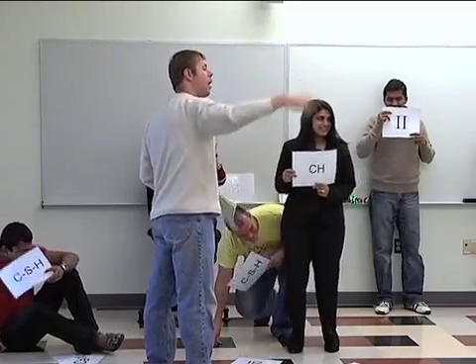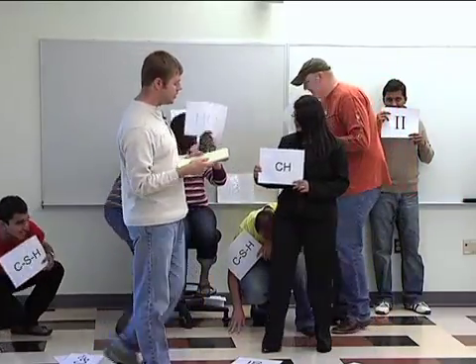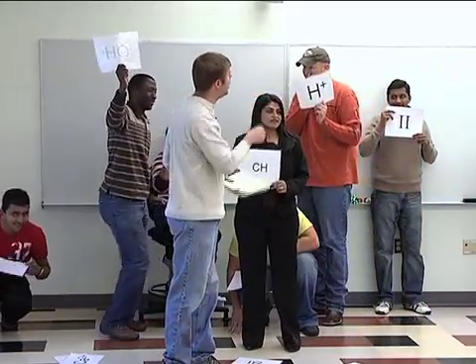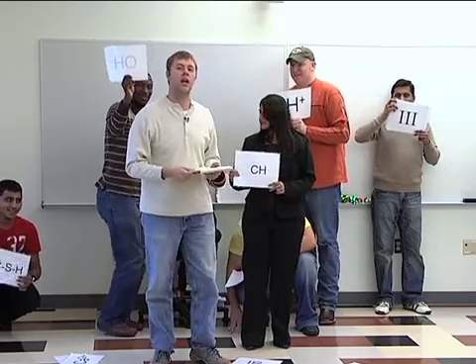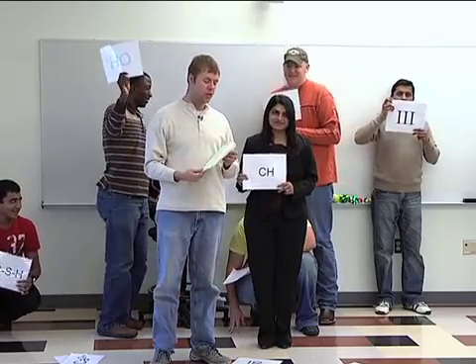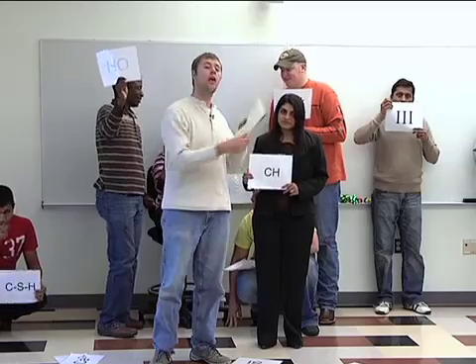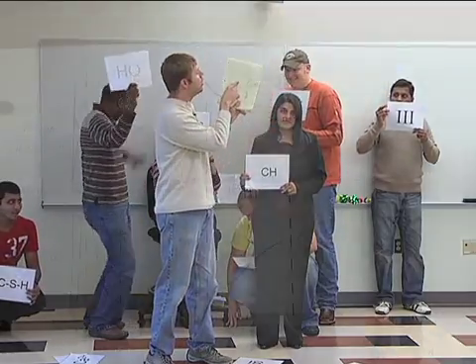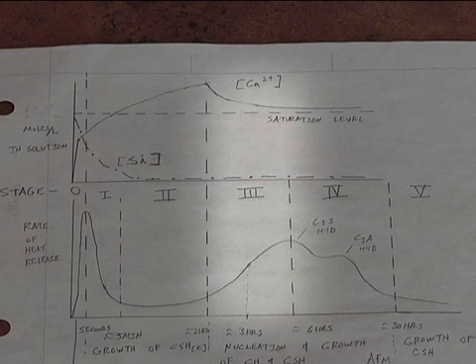All of a sudden the water comes running back in. All of a sudden we have the beginning of stage three. This is the beginning of stage three and we have massive reaction. We have massive heat given off. We have heat going up and up and up. We have tons of water molecules coming in, more ions going into solution, more CSH being formed.